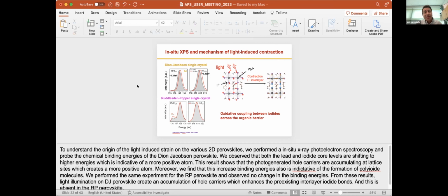That's a great question. In fact, we wondered about this a lot. And what we think is happening to the lead is that obviously the lead hosts the electrons, right? And so the electronic states are quite delocalized. So the hole gets localized on the iodine, but the electron gets delocalized. And so what we think is happening is that the lead is observing a secondary effect which comes from the iodide. And so that's why we see a shift also towards a blue shift.